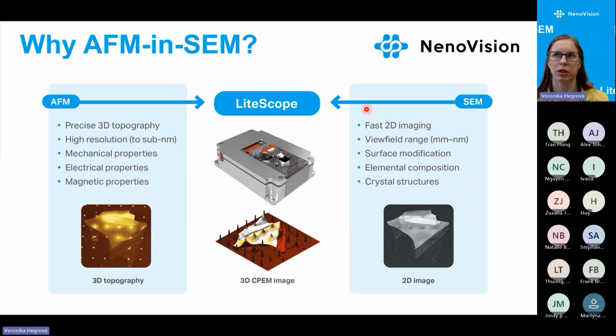But first I'd like to start with a question, why the AFM in SEM? So both of these technologies, instruments, are measuring sample surface at nanoscale, and they are using different principles of operation. So we are able to measure different properties and correlate them together at the same time in one place under the same conditions. We are able to measure 3D topography with very high resolutions, mechanical, electrical, magnetic properties, and combine it together with quite powerful techniques from SEM capabilities, fast 2D imaging, from wide field range to a very high resolution in XY direction. We can modify the surfaces using focused ion beam or gas injection system, measure elemental composition using EDS, or measure crystallography structure.